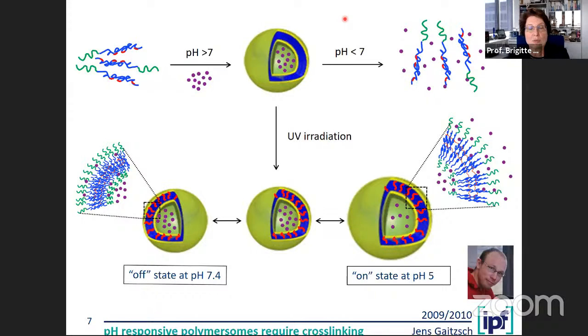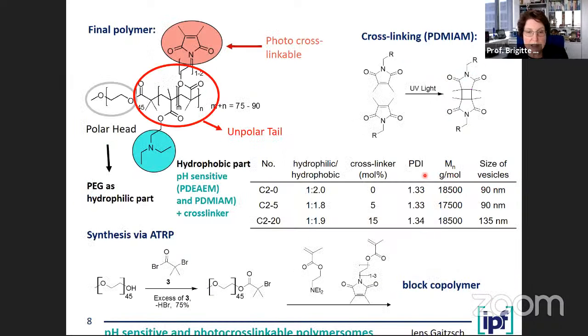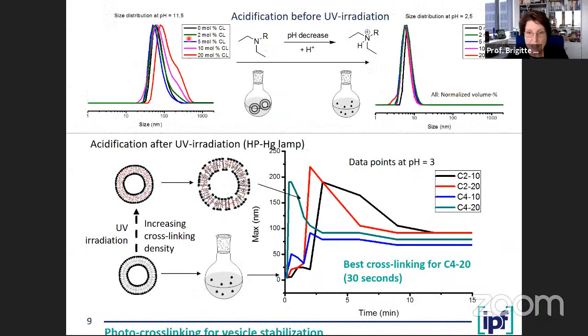And if this is working well, and it worked well in our case, you can actually avoid disassembly, and you can swell and deswell the vesicle, the nanocapsule, and get an on and off state of that material, where the membrane is leaky or the membrane is closed, and that worked very well. Okay, the chemistry behind is controlled radical polymerization. We used ATRP in that case to make a block copolymer having a polar PEG chain and a less polar middle chain, which contains a pH-sensitive unit, in that case this tertiary amine. And it contains a cross-linking unit, as you see here, which can be photocross-linkable. The material can assemble depending on the pH.